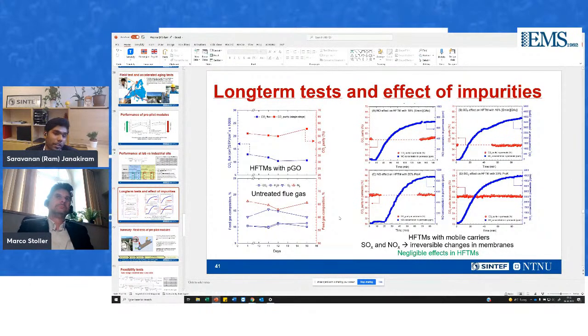Very good comment. It's quite expected that when you have small molecules with CO2 affinity, they can be very prone to unstable conditions. So what we wanted to do was a bad postmortem test, where we exposed the most vulnerable system to the worst possible conditions. For the Sheffield study, we actually sent the membrane modules which have mobile carriers, not the membranes without mobile carriers. So the graphs that you see on the right are membranes having mobile carriers.